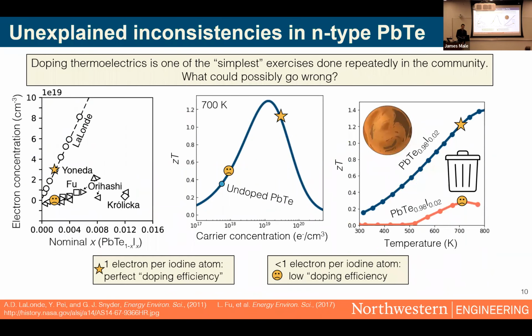So the first thing I want to touch on is these inconsistencies in doping N-type lead telluride. So to make lead telluride an N-type semiconductor, you can add a dopant like iodine on the tellurium site. And if everything goes according to plan, every single iodine atom would give you 1 electron, which represents perfect doping efficiency. However, you see a lot of authors who report far less than 1 electron per iodine atom in their lead telluride, which represents a really low doping efficiency.